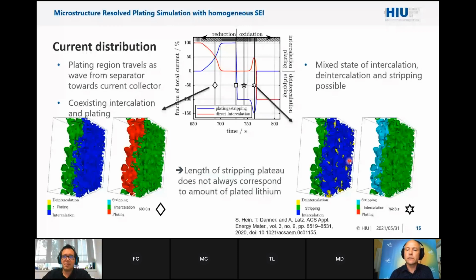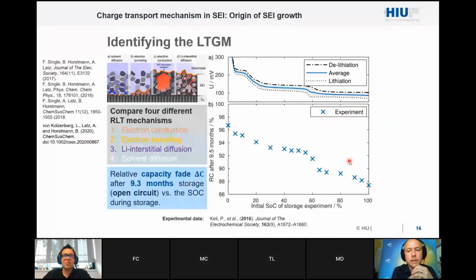So this was a simulation with a homogeneous SEI film. We developed in recent years, starting actually from 2015, a very detailed picture for SEI growth. We compared in detail different mechanisms for what is responsible for the SEI growth: electron conduction, electron tunneling, solvent diffusion, and some mechanism which was motivated by